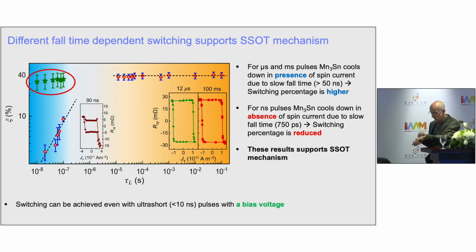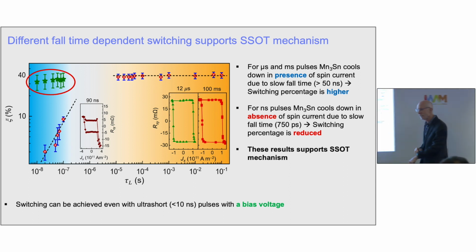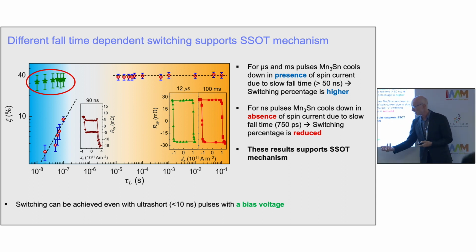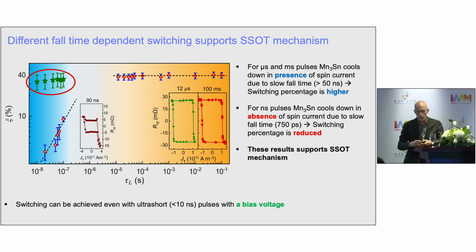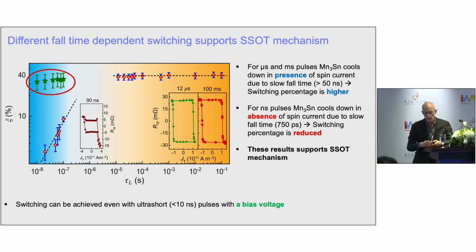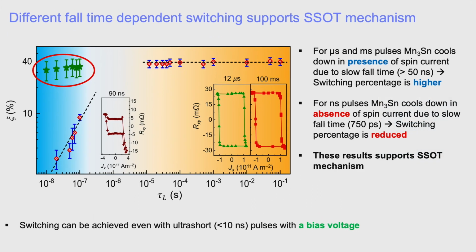So we believe we've demonstrated that the mechanism for switching of these chiral antiferromagnets is distinct from the pure spin-orbit torque mechanism that was originally proposed by this group in Japan. Rather, it's totally different. It's a combination largely of heating above the ordering temperature and cooling down by this seed layer in the film that is set by the spin-orbit torque itself.